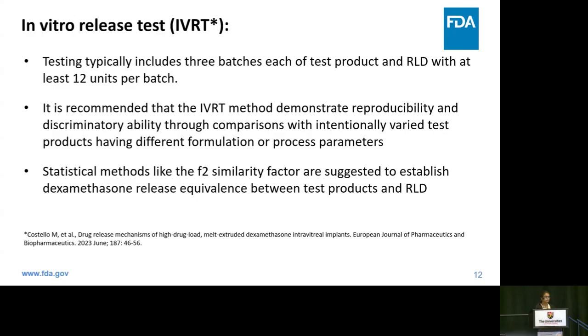It is recommended that the IVRT method demonstrates reproducibility and discriminatory ability through comparison with intentionally varied test product having a different formulation or process parameter. So, varying material attributes, for example API polymorphism or API particle size. Then the second is process attributes, by changing the particle size distribution, or by changing formulation attributes such as drug polymer ratio. By doing those discriminations, the applicant needs to show that the provided IVRT method is specifically unique for this particular test product, and statistical methods like F2 similarity factors are suggested to establish dexamethasone release equivalence between test product and RLD.